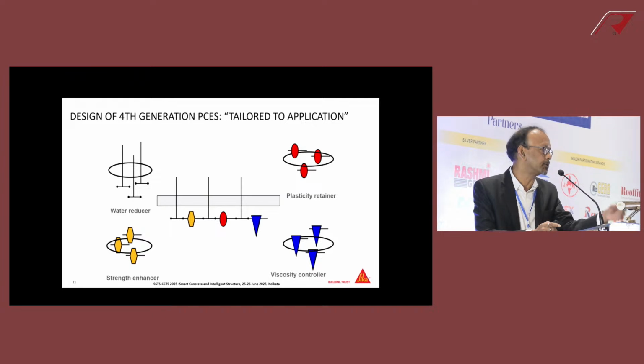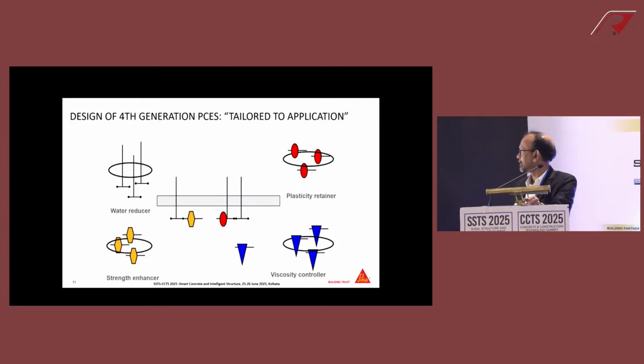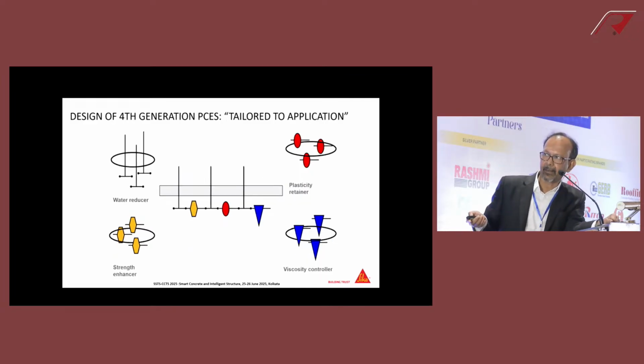Today, when we go to ready-mix companies' requirements, especially in crowded cities like Bangalore, etc., you require 4 to 6 hours of slump retention without loss of the quality of concrete, and you do not add water in between during the concrete transit time. So this is how design happens.